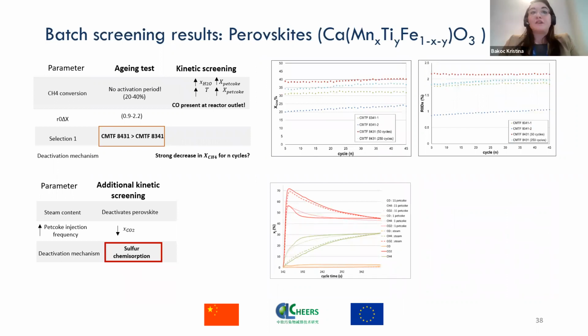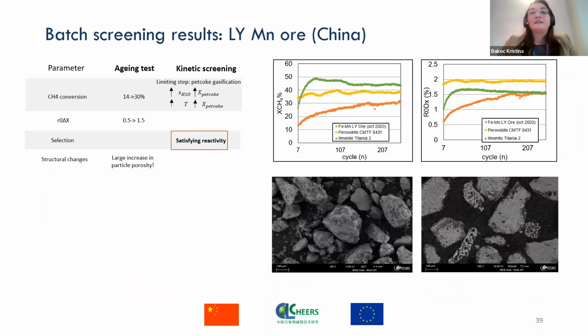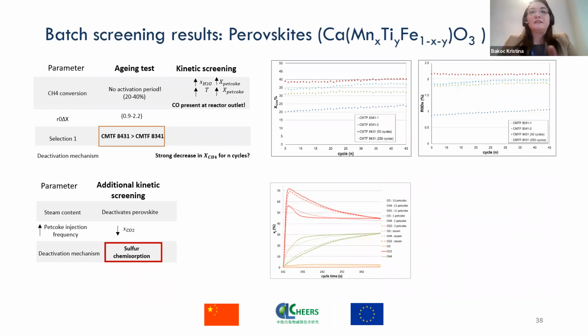Following with the results of perovskites, they are the only synthetic materials. And as you can see here, they have no activation periods that were noticed during the aging tests. However, for similar gas flow rates, somewhat lower methane conversion was observed than with the previously seen ilmenites. Also, we have found a certain decrease in activation for repeated redox cycles. And for this reason, we decided to perform additional kinetic screenings.